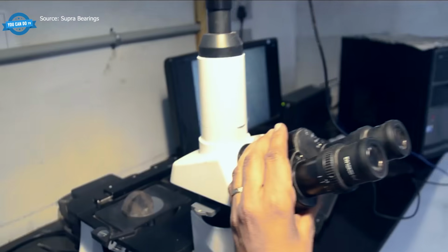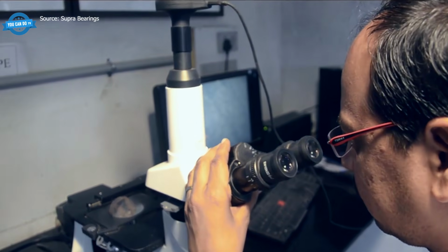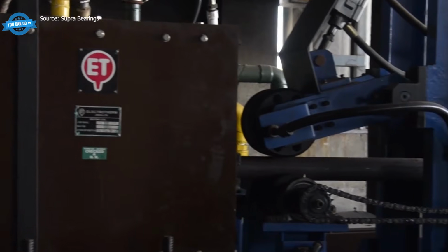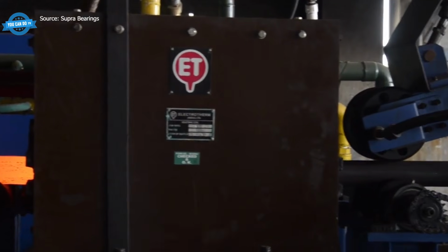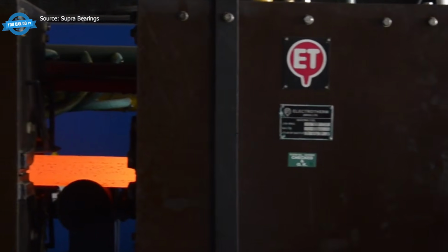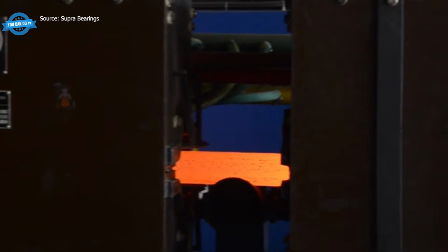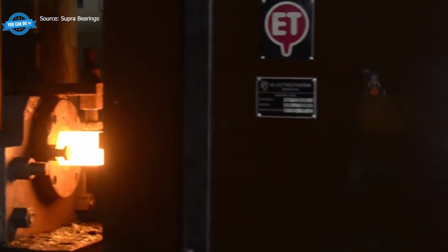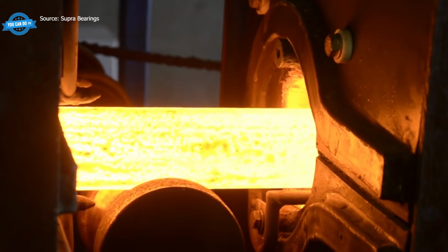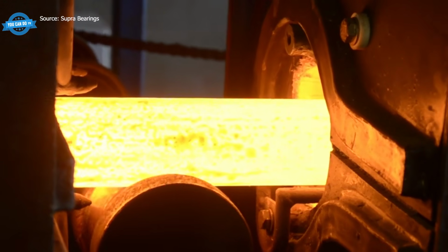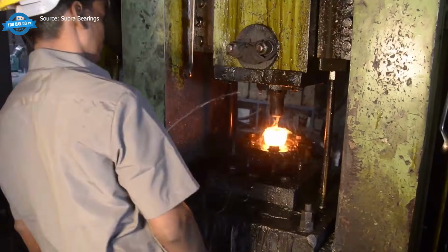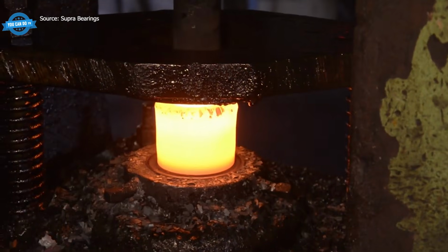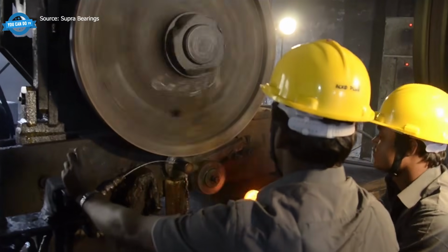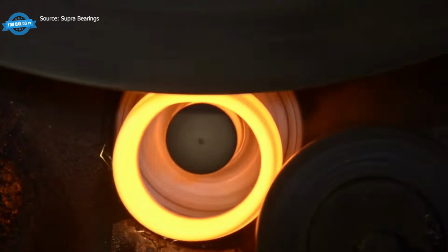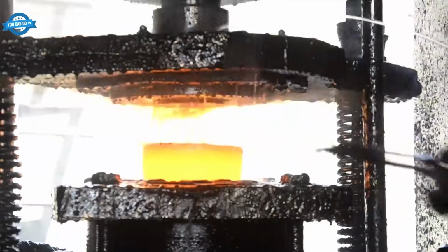Bearing production is forging and grinding, in that order, for a very long time. Rods get forged into rough rings. Rings get turned, heat-treated in salt baths, quenched, then ground to final size. The grinding sparks look aggressive, but they are removing microns at a time. After that, roller cages get pressed from sheet, rollers are cut and tumbled, and the whole thing gets assembled by hand. Now the rings roll aside for the shafts.